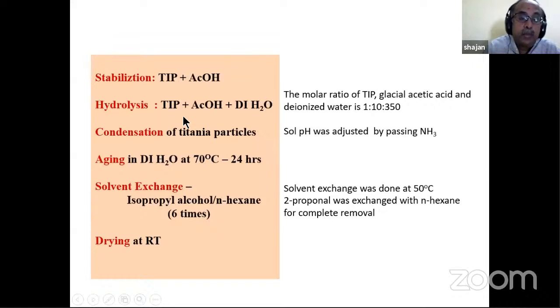That is the point where we get the sol, which is then condensed by passing ammonia. So we are adjusting the pH of the solution to suit condensation. We want to convert it into a gel, and we allow it to age for about 24 hours at 70 degrees centigrade. Now we get a gel, and this gel undergoes solvent exchange.